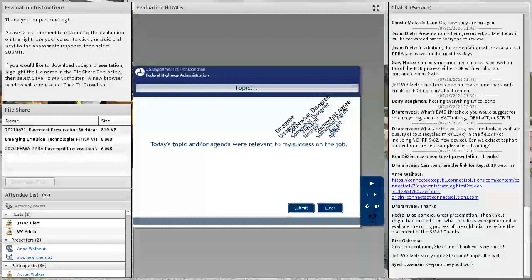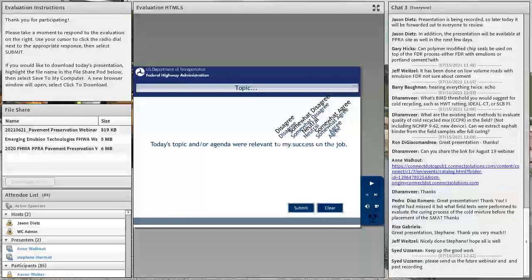So when doing the ITS, when compacting the sample in the lab, of course you're going to get the density. You run a GMM, calculate air voids, and I think the key is to see how close it is to the mix design. Also, if you do control charts, you can monitor the changes over time. That's what we usually do for the quality control of the mix, going to the paver, going to the road.